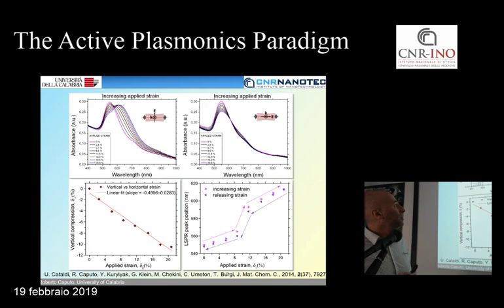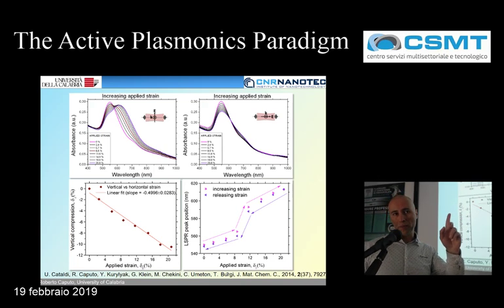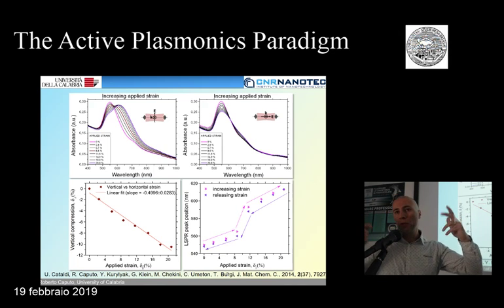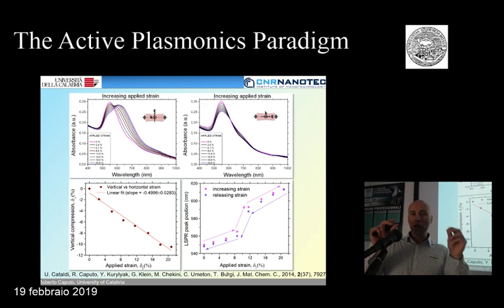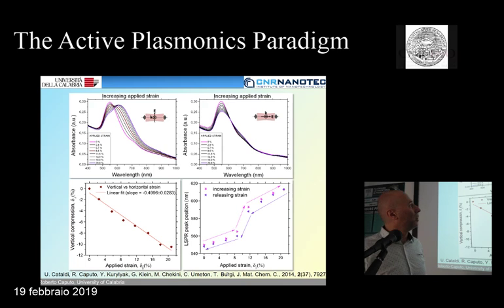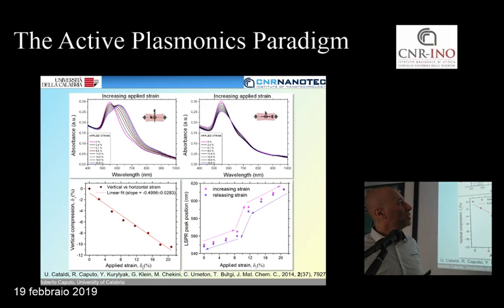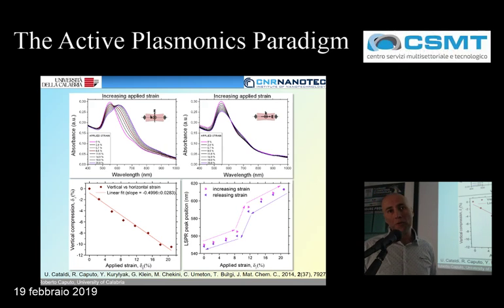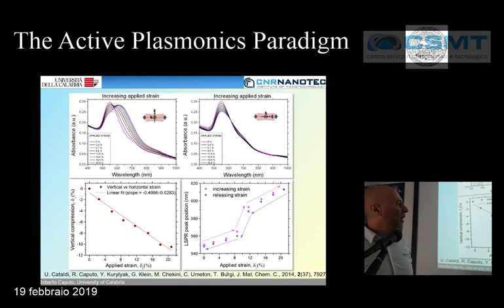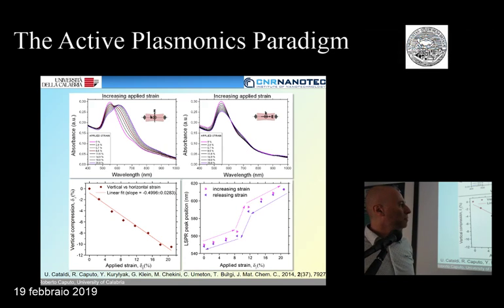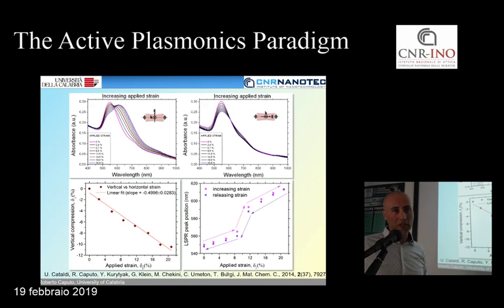And it's about 80 nanometers for the exciting polarization of light which is perpendicular to elongation. When you consider the other polarization, along the stretching direction, the nanoparticles don't get coupled because they go away from each other. So you just have a decrease of the amplitude of the plasmon resonance. This is due to the fact that you illuminate fewer particles when you stretch them. As I said, this is quite reversible, and we remained in the elastic behavior of the substrate.